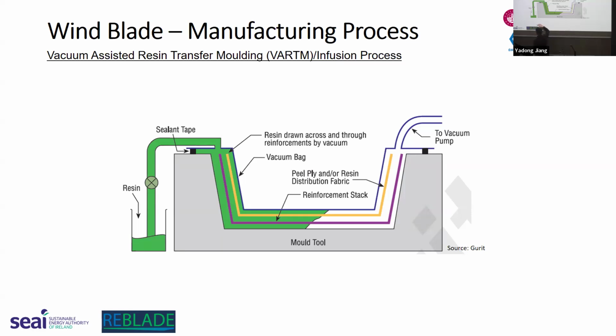So when you turn on the vacuum pump, you will suck resin from the resin pot and into an inlet, which is a port in your vacuum bag. As I mentioned, the vacuum bag here is this purple line, and the sealant tape is what seals it so that the air doesn't get in or out. As the air is leaving the bag and creating a vacuum, it creates a pressure differential and sucks resin from the resin pot through your mold, and your dry glass fiber wets out, and then you just shut off the valve once everything is wet out.